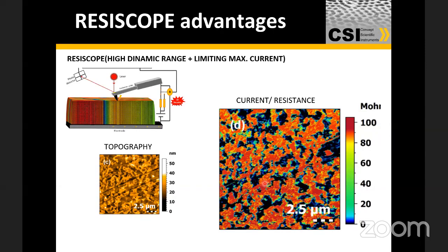So, yeah, but nowadays you also have super sharp tips. The super sharp tips are down to about 2-3 nanometers, and then there's an atomic layer coating on it. But the problem with the coatings, as we have just discussed, is that these coatings can burn off, typically. So that is why you're better off with a whole diamond tip.